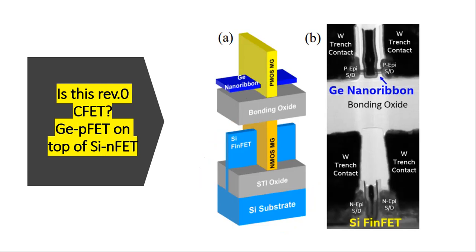And this is, I think, impressive work because it's very difficult to get a pure germanium PFET to work properly, because the native oxide is very bad. The passivation in the interfacial layer is very critical, not to mention the process. Germanium oxide dissolves in water. So it's not like SiO2, which is so good, so strong. It can only dissolve in HF. It's so good, right? But germanium oxide is naturally pretty bad.